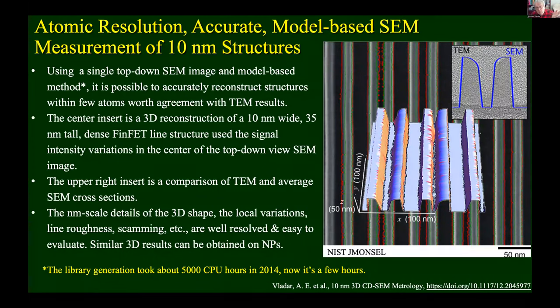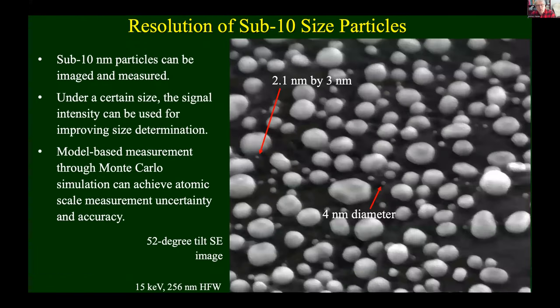This was based on putting physics to work, meaning we generated a library where the possible waveforms connected to the different geometry of the structure were modeled ahead. And then out of that library, which at that time took about 5,000 CPU hours, now it can be done in a few hours, allowed us to figure out exactly which one fits a certain location. And you can see that the match can be very good. So these are actually showing you atoms, there's a few atoms worth of difference in this particular case, and also the confidence in these results was established by X-ray scatterometry measurements.